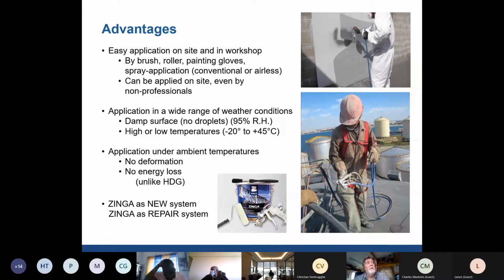You have no limitations. Where most projects stop, when the inspector on site says that 70% humidity, you've got to stop spraying now, with Zinga you don't have to do that. In fact, we proved this in Akosombo, a big project we did in Ghana. Every morning, because of the mist, the relative humidity was always up in the 90s, first thing in the morning. With paints, they couldn't apply anything before 10:30, 11 o'clock at the earliest. But with Zinga, they could go in there and start working 8, 9 o'clock as normal. So time-wise and cost-wise, it makes a big difference.